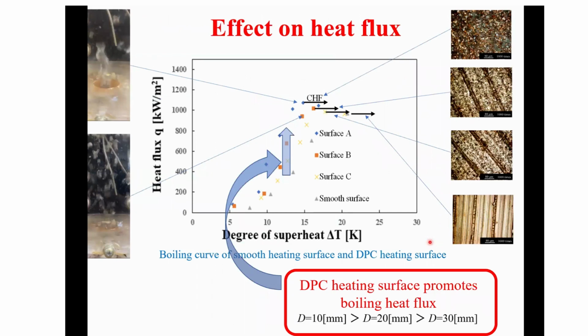This is a result of the heat flux versus the degree of superheat. The abscissa is the degree of superheat. The ordinate is the heat flux. The different symbols are different surfaces: artificial surfaces and the smooth surface here. The result is here. And this is the smooth surface. The three different surfaces differ only in D. The narrowest spacing is D equal 10 millimeter.